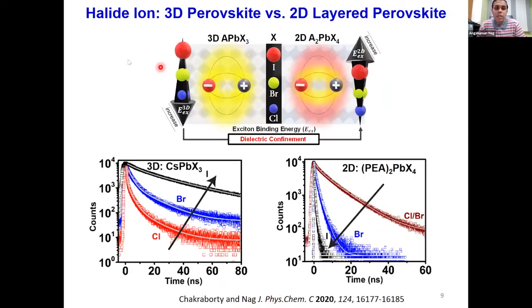So this dielectric confinement that I discussed here also gets manifested in terms of halide ion composition. If we keep other parameters the same and just change the halide ion composition, we know that in a 3-dimensional lead halide perovskite, as you go from iodide to bromide to chloride, the excitonic binding energy increases. However, because of this dielectric confinement, when you come to layered perovskite, you see a reverse trend. When you go from chloride to bromide to iodide, the excitonic binding energy increases. So this is the reverse trend of halide dependence: in 3D perovskite, the excitonic binding energy increases from iodide to chloride, but when you go to 2D layered perovskite, it is the reverse trend.